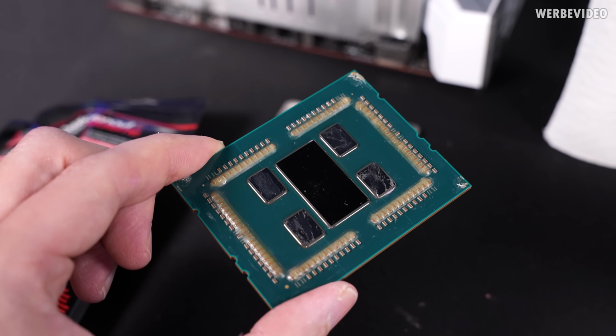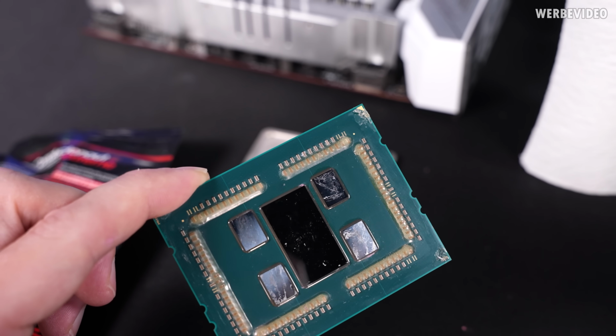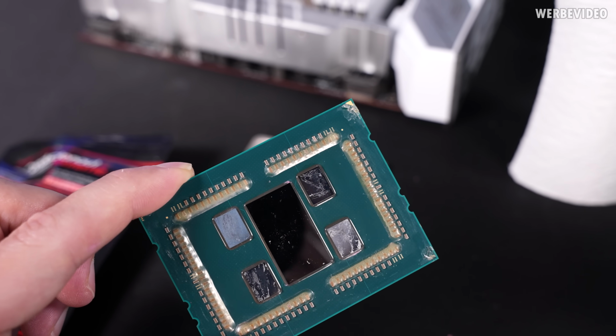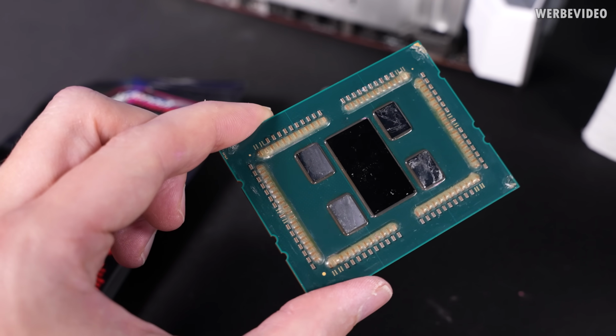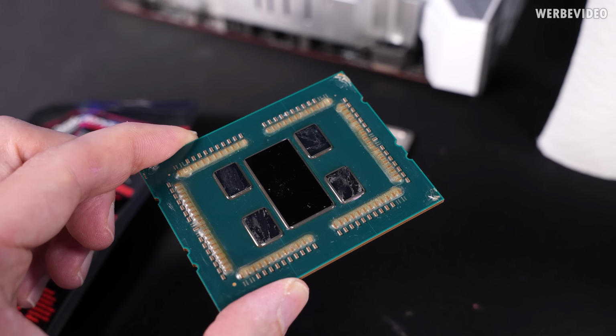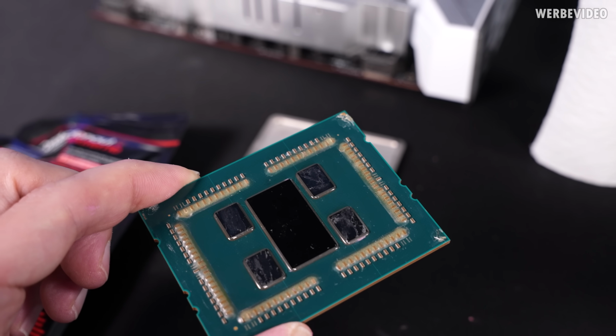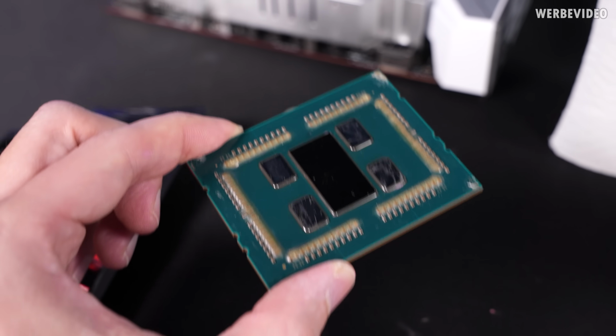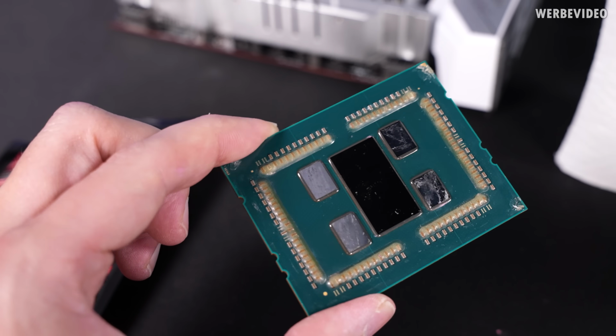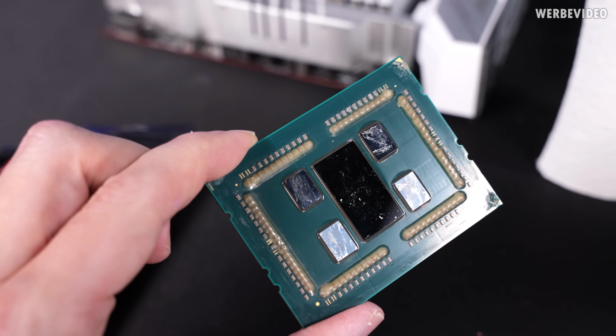I meanwhile also spent time to clean the CPU, as expected. There are only very little scratches and residues left on the silicon dies. As expected, we know there is not really an interaction between the gallium, indium, and the silicon itself.